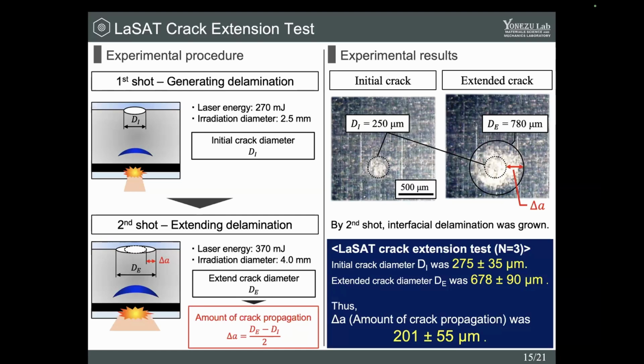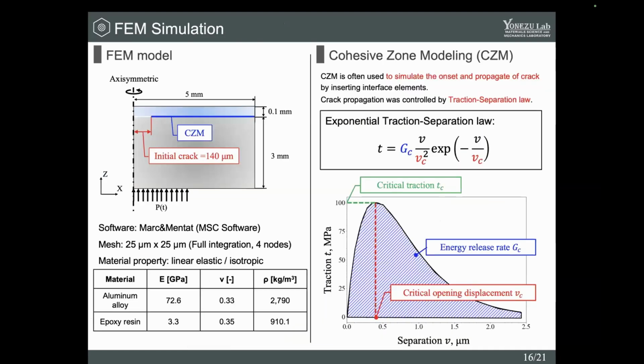As a result, we calculated the amount of crack propagation as about 200 micrometer. In order to determine the impact of fracture toughness from laser crack extension test, we conducted FEM simulation with initial crack and CZM. This study used exponential traction separation law like this. Other analytical conditions were same as before.